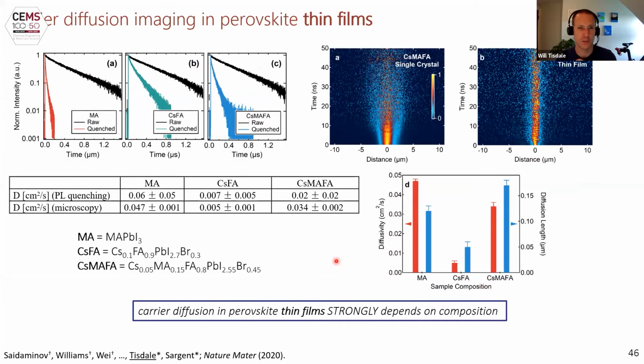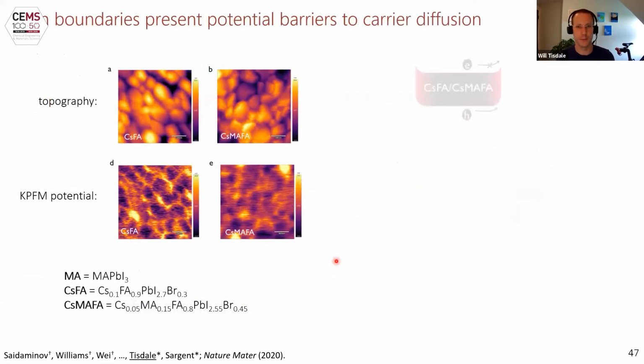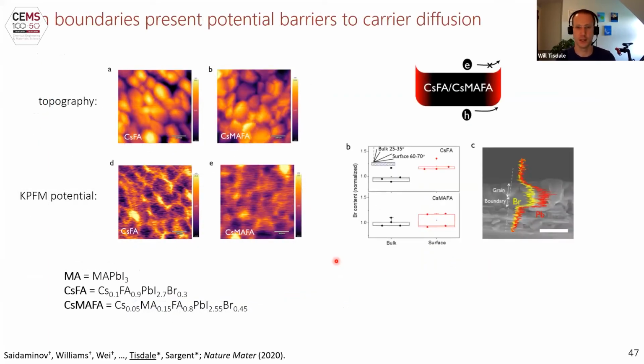To reinforce our measurements, because we're getting all this information from the time resolved microscopy measurement, we wanted another technique to verify. We did a thin film quenching experiment, which quantitatively within our uncertainty verified the results of the time resolved microscopy. Okay, so what's going on? The overall story here, I think I'm getting a little long-winded in telling the story, but the overall story here is that there is halide anion segregation within the grains, and that the grain boundaries tend to become bromide rich.